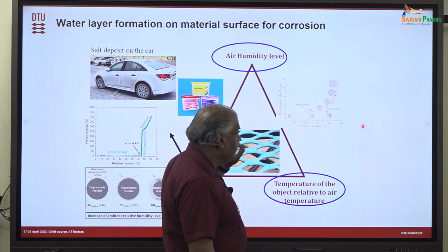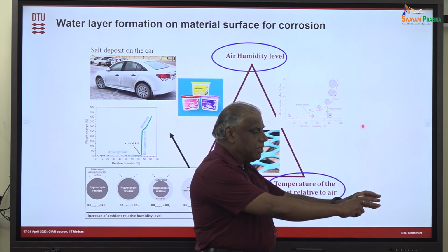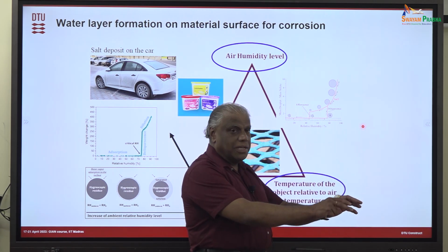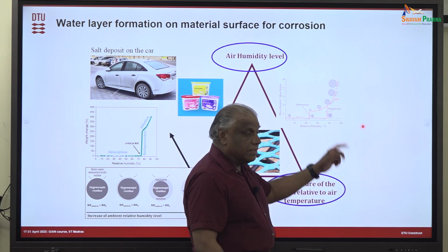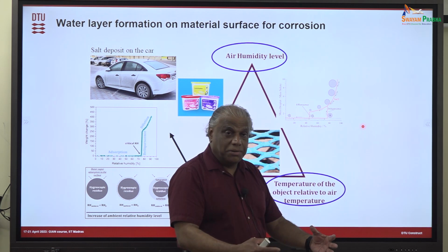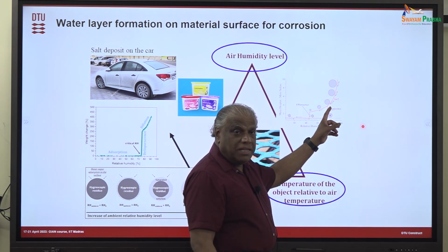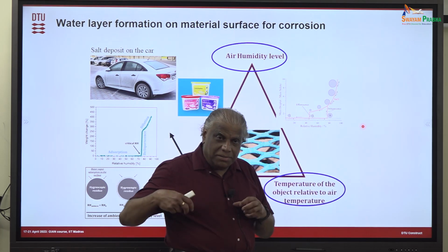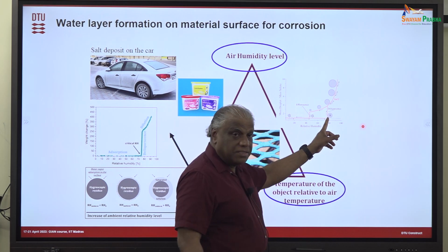What it shows is, if you take sodium chloride, you keep increasing the humidity. So you have sodium chloride here, and above that sodium chloride, you keep increasing the humidity level. When it becomes 75%, suddenly you will see that sodium chloride becomes a liquid. Then what will happen? Now you remove the humidity. You start removing the humidity. So you expect that it will come back and crystallize.